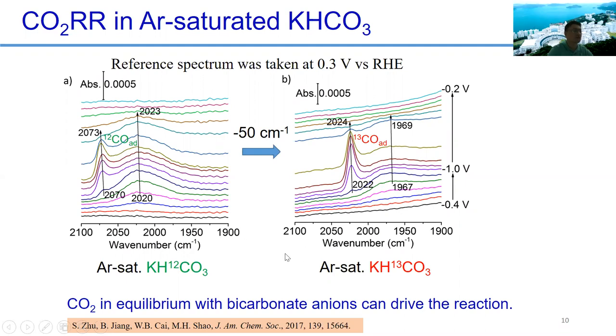So we further used isotopes. Using carbon-13 in the electrolyte and still without any CO2, we can see the same peak rise, but at a different position. And we definitely confirm this is due to CO, because of the shifting of the wavenumber by using the isotope.